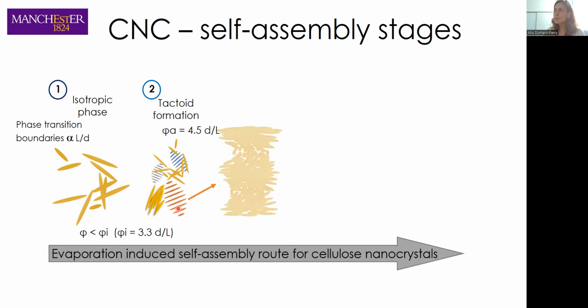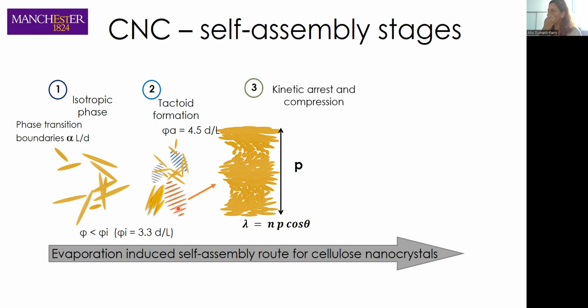As the evaporation progresses, we have a more condensed suspension where more interactions are taking place. What's happening is that the tactoids are starting to merge with each other. The planes of the nematic phases are also sedimenting at the bottom, through the solid interactions. Because we are casting a film on a solid substrate, if you remember, that also is regulating what's happening in this Petri dish.